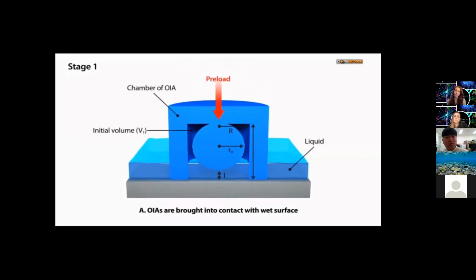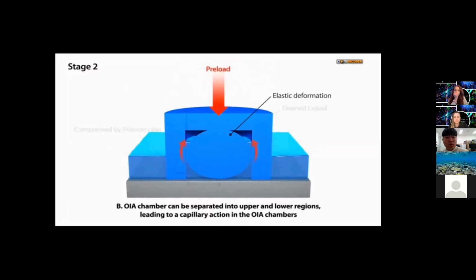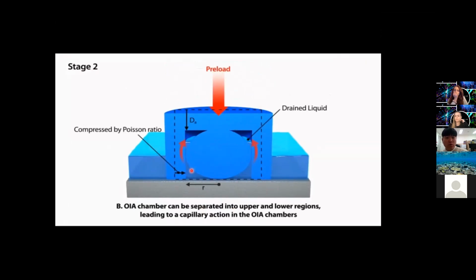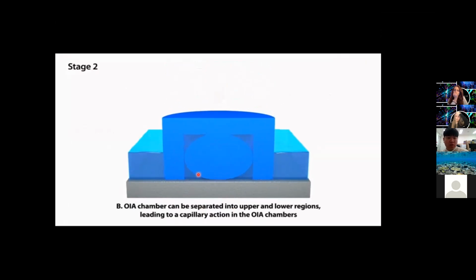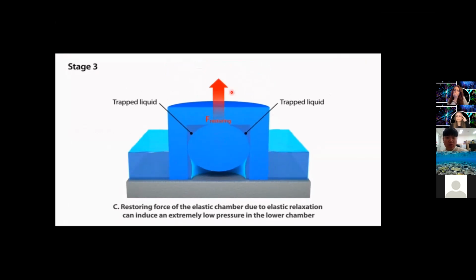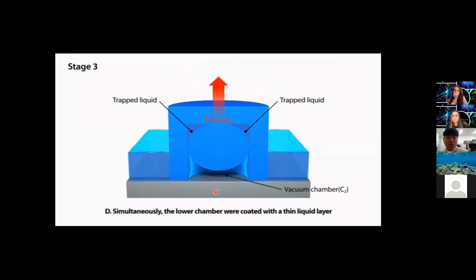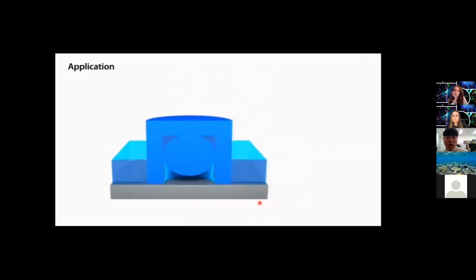First, the octopus-inspired patch is brought into contact with the wet surface. During application of external preload, the sphere and the sidewall inside the chambers are in contact. This contact can separate into upper and lower regions, leading to a capillary action. After removing the preload, the restoring force of the elastic chamber can induce an extremely low pressure in the lower chamber. Simultaneously, capillary bridges in the lower chamber can prevent the leakage of air.